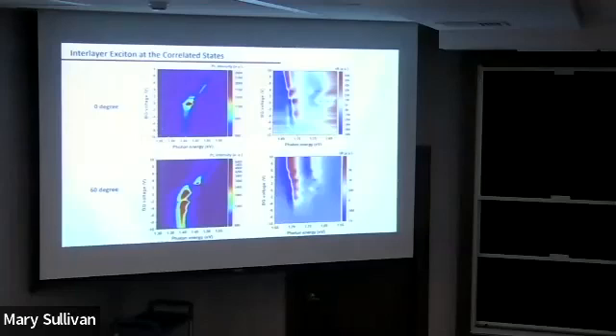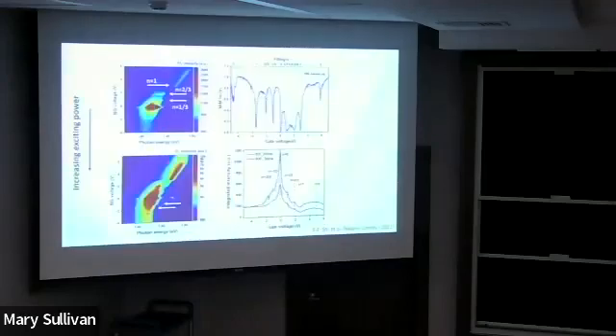So we took the PL. This is for the 0 degree, 60 degree sample. You can clearly see PL actually shows the 1 and -1 states here, corresponding to the reflection measurement. But what's more, if you zoom in on this particular sample, the PL is already showing 1/3 and 2/3. Here, the PL is much more sensitive than the absorption measurement, simply because this is a background-free measurement. In addition, if we increase the power, we actually can see previous states, which were not there, showing up. For example, for this particular data, we can see that at a higher excitation, you have n equals 1/3, 2/3,